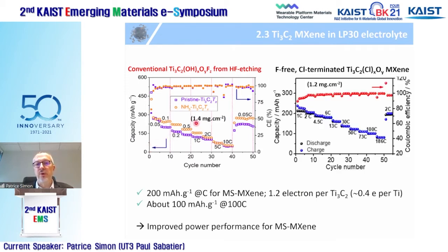Now, if you compare with the molten salt MXene that we prepared, with the same weight loading between the two electrodes, 1.4, 1.2, you can reach about 70 milliampere per gram at 186 C. So it means that first you start from 200 milliampere per gram at low discharge rate, which is very decent, and you can still deliver at 100 C, in a 0.6 minute charge discharge, 100 milliampere per gram.